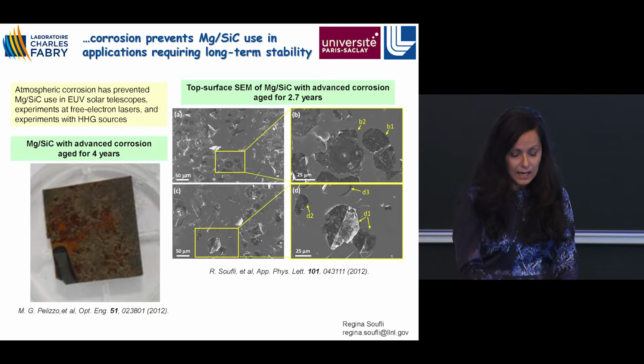So what you can see here is this catastrophic corrosion. This is a scanning electron microscopy, SEM image of the top surface. It appears spontaneously and suddenly after a few months in air. You see here regions that seem to be exploded on the top surface of the multilayer. This is a zoom. These regions you can see here, they look like a crater that has just exploded. Material seems to be missing, or material is peeling off, like you peel off a sticker almost from the surface.